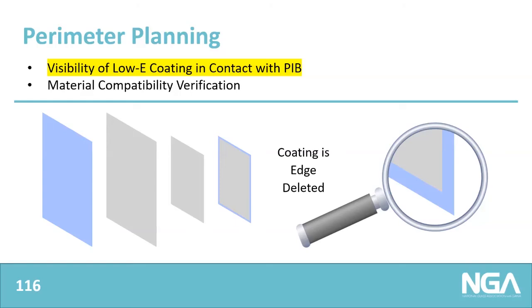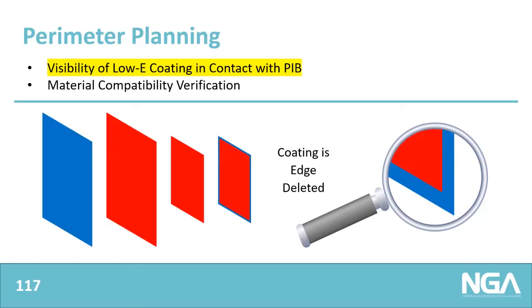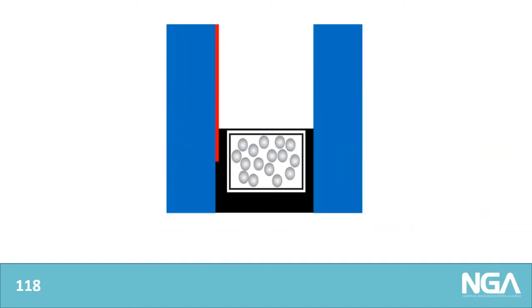Now, in regard to this aesthetic issue that we're getting to, let's change the color scheme for amplified visibility. We'll make the coating red, as you can see there, and the glass deep blue. And we'll take a look at the edge of an IG unit in profile. So we have the outside of the building to your left, the inside to your right, the coating on the number 2 surface. We have primary seals P and a secondary seal S. And those letters also correlate with the common sealants that are used, probably the isobutylene, PIB, and silicone as the secondary seal.